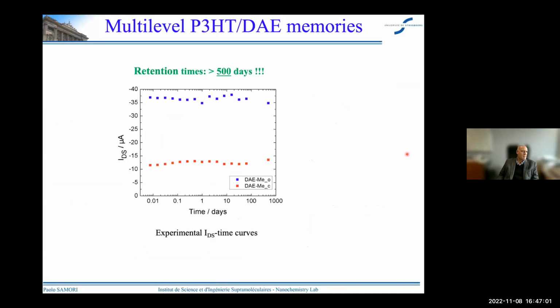Now, of course, when you fabricate a memory, it can be your USB key, can be your hard disk of your computer. Retention time is very important because you want to come back the day after to have, let's say, your information, your data that is still stored in your hard drive. And so we were lucky that this work was published in a very slow journal, and actually we could explore our device over a very long period of time and have a retention time that's exceeding 500 days.